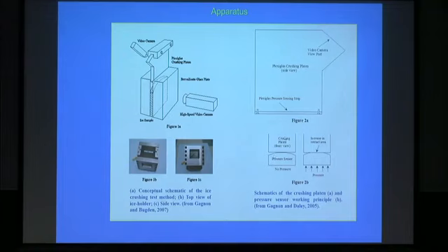When a load was applied, the width of the contact was a direct measure of the pressure. I actually have a little mock-up showing how that works for anybody who would like to see that afterwards. That technology we've used extensively, both at small scale and at big scale, to measure pressure during ice impact and indentation.